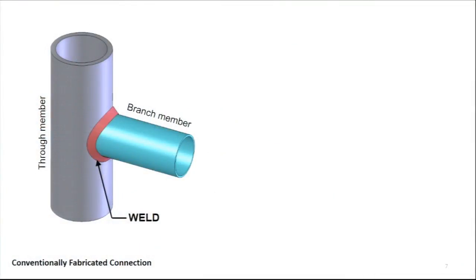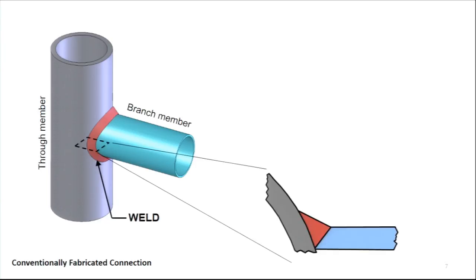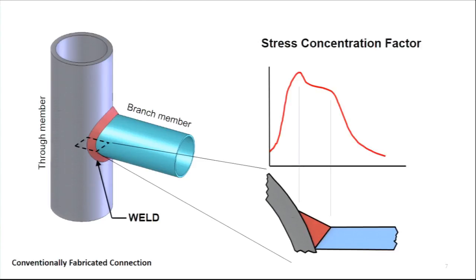And the way that cast nodes work in that sense is actually very simple. If you think of a conventional weld fabricated connection, we put the weld really in the worst possible place we could think of. It's right where the geometry is complex, right where your forces are highest, right where your stresses are expected to bend the corner. So you can see in, say, for example, a tube-to-tube welded connection, that welded joint has got a very high stress concentration just by virtue of the geometry of that connection. But it also has a high stress concentration factor because welds inherently have defects in them. And so if I look at the stress concentration going through that connection, I get a very high spike at that welded joint. And so if I load that connection in a fatigue type regime, after a certain number of cycles, that connection will fail at that welded joint.